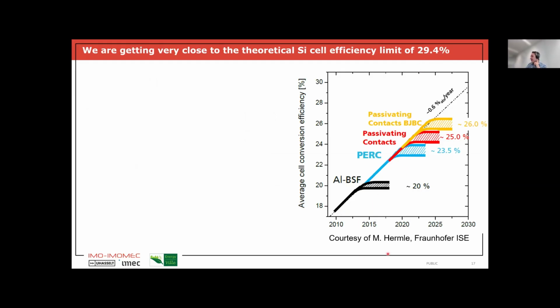So in the past, colleagues from Fraunhofer ISE made this roadmap for different device structures and the efficiencies that we can reach in mass production. And mass production efficiencies will always be a bit lower than, of course, the best you can do in the lab. And so they foresee that at this time, which is correct, we are producing the passivating contact devices, where probably we can reach at module level, or let's say at mass-produced cell levels, efficiencies around 25 or slightly higher. Then we will at some point switch in the industry to the passivating contacts with the back contact solar cells, where we can probably reach around 26%. But then it's basically sort of stopped.